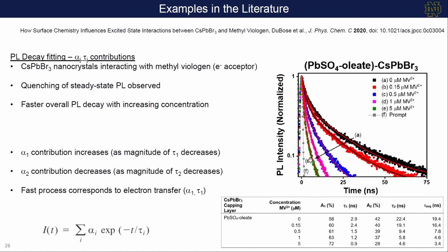So again, we would want to be careful in specifically talking about the individual values for the components of this. It'd be better to talk about this trace specifically as more or less prompt limited or instrument response limited. But again, I think this is a nice example of, to what degree do you want to actually be confident in saying this? You should probably take the actual values for this decay trace a little bit with a grain of salt.